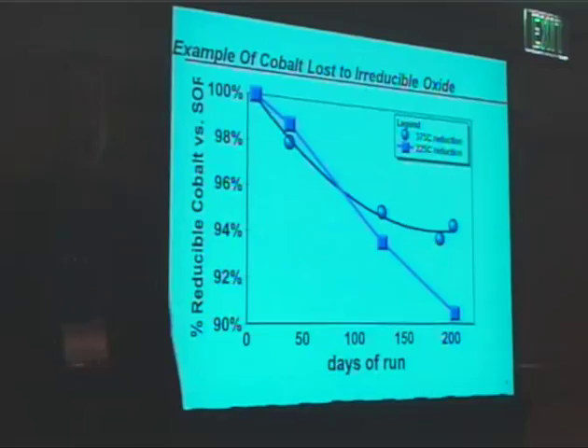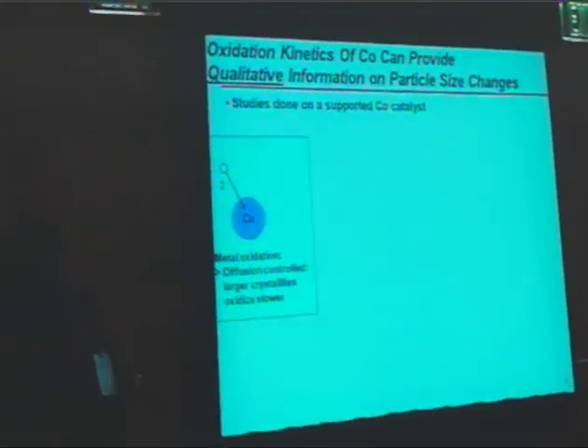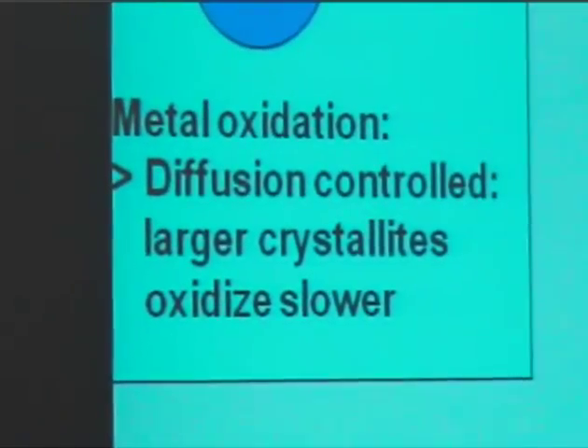If you can go to 375 reduction, well, the loss isn't that bad. That extra 150 degrees C gets some of it back, okay? But that's a loss. So this could be a loss, not a huge one, but one that you need to be aware of. The more serious losses that you can have come in the agglomeration. And that's what we want to spend a lot of time talking about now.